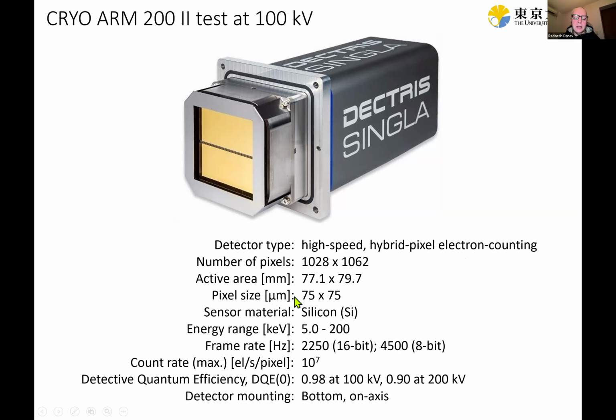Of course, the detector has a very large pixel to be able to do that. You see here 75 by 75 microns. That's 15 times larger, I think, than the typical direct detector now in electron microscopy. Also, the chip itself is much larger, so when it's mounted on the microscope, it's also a much larger area. And it's composed of two modules. You can see them here, and there is a gap between the modules.